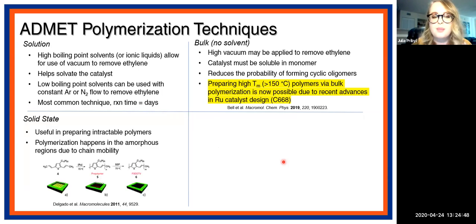Another couple of techniques I want to talk about are what I call kind of boutique. They're not used very often, but they are effective if you need to use them. First of which is solid state polymerization. This is useful in preparing intractable polymers. And the polymerization primarily happens in the amorphous regions, because that's where there's the highest degree of chain mobility.